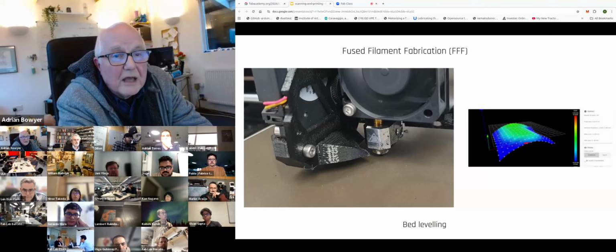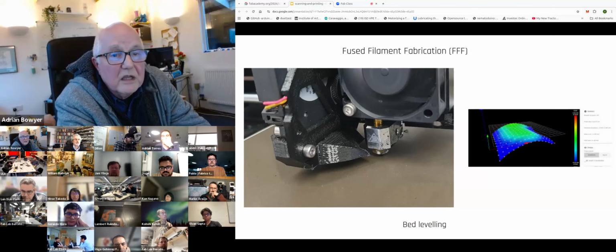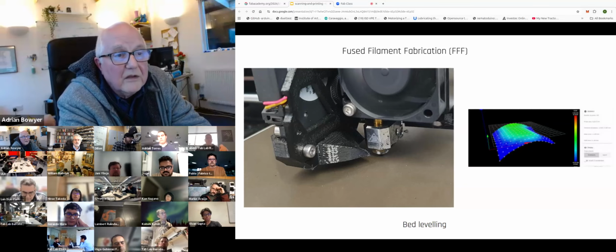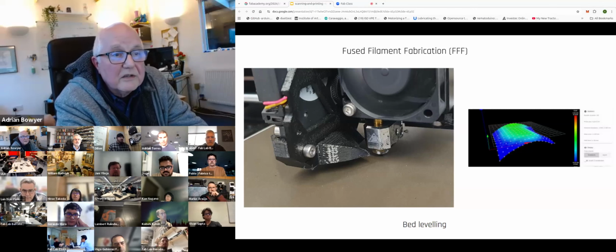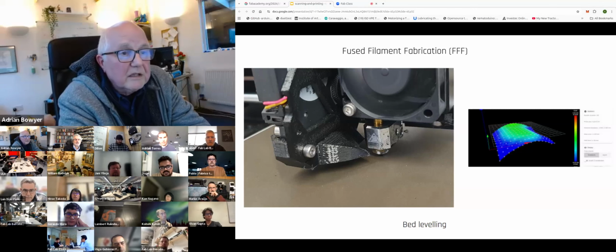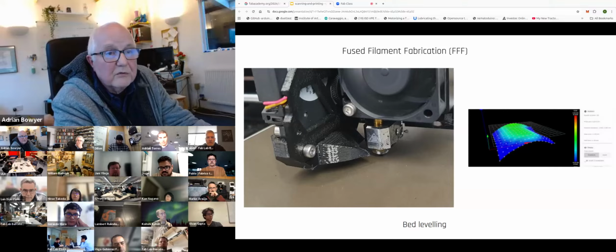The machine can then use that map when it's actually doing the print in order to move the head very slightly up and down to get a consistent distance between the nozzle and the bed. This is very important so that the very first layer of the print adheres strongly to the bed and doesn't detach itself. And as I say, this is a trick that almost all modern FFF 3D printers can do.